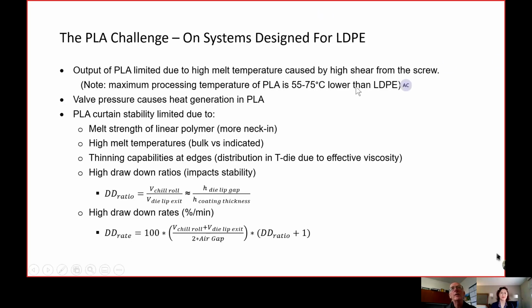So we're going to be limited in the extruder output, not because we can't pump that PLA, but because that PLA will go over the target temperature that we want. Additionally, there's often a back pressure valve, which again puts more shear energy into this. So it's very difficult with this arrangement to keep the temperature down at a reasonable output.